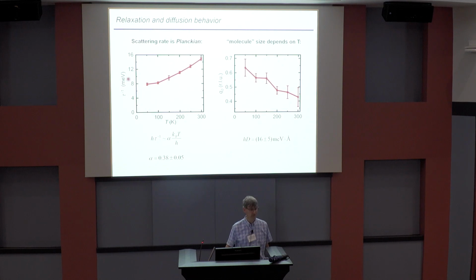So tau has units of MeV, that's actually h bar over tau, but tau to the minus 1 is actually an MeV, and T is temperature, so there's no fitting. You can measure this alpha, it's an actual number, and it's of order 1. I had a debate with my student, is 0.38 of order 1? He said, well, it's less than of order 1. I said, no, it's not, it's less than 1, but it's not less than of order 1. That doesn't mean anything. D is constant as far as we can tell. It's 16 MeV angstrom plus or minus 5.